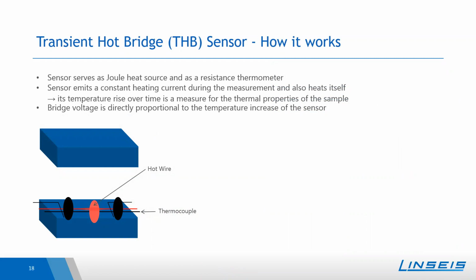All of these sensors serve as a Joule heat source and at the same time also as a resistance thermometer. So during the measurement, the sensor emits a constant heating current and heats itself. The temperature rise over time, recorded with the resistance thermometer, is then a measure for the thermal properties of the sample. So in the transient measurement method, you bring a thermal disturbance into the material and detect how the material reacts to it with time. Based on that, one can then determine the thermal conductivity.